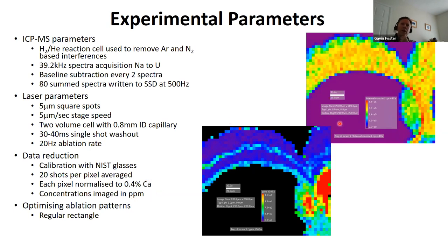So this is what we generated during initial optimization, sort of maps. A bit of a problem that we noticed really was that there's a lot of area because they're hollow. We mount the forams, so the forams are like a bunch of spheres. We mount that in resin, and then we polish through that resin to expose a cross-section. And so we get a good cross-section of the wall, which is about, in this case, about 40 microns, but there's a large area that's just resin that we don't really want to measure. We don't really want to put loads of resin in the machine, and it's sort of wasting time. So 40% of the area is of no interest, and like I say, it's wasting time and cost.